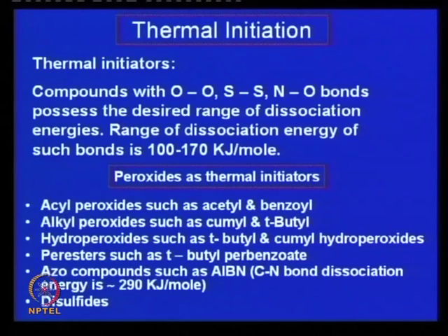Thermal initiators contain O-O bonds, S-S bonds, N-O bonds that possess the desired range of dissociation energies, which lie within 100 to 170 kilojoule per mole. So, chemical compounds having such bonds can act as thermal initiators.